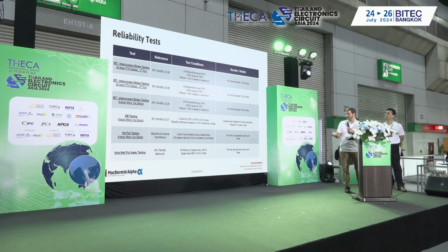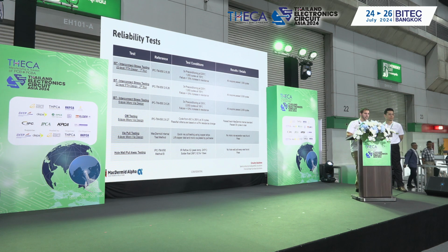All of these tests for all the conditions passed. You can read the passing here. But there was no significant issues found in any of the tests. Again, showing reliability was fairly consistent between our electroless process and DC process, or primary metallization process, and consistent between our DC process and our pulse plating process.